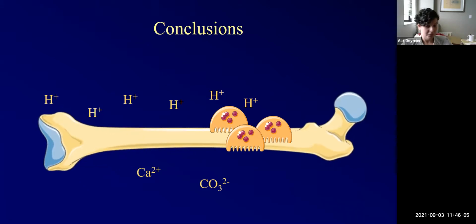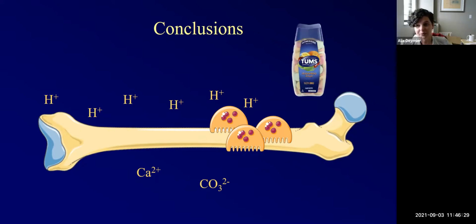When we put this in acid, that's enough, the toughness goes up. So even though biologists love to tell you that the cells are the key factor in bone changes during acidosis, the mechanical behavior, which seems to be honestly the most important, isn't caused by the cells. It seems to be regulated by the physiochemical mechanism. So instead of giving bisphosphonates to people with acidosis, indeed, we should just be giving them Tums. Bringing down that acid, getting it so that the physiochemical dissolution stops. That seems to be the best way to stop these mechanical changes. So there's obviously plenty more to do, but we've really learned a lot over the last 4 years. My lab's only been here for 4 years, about how this bone interacts at the physiochemical and cellular level.